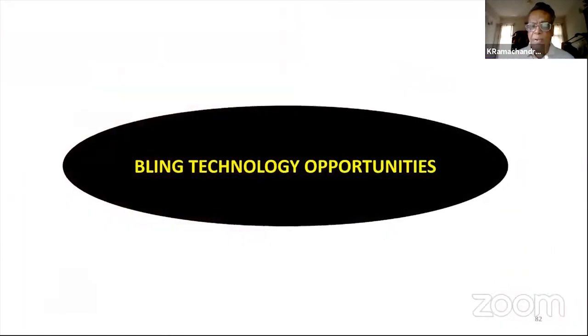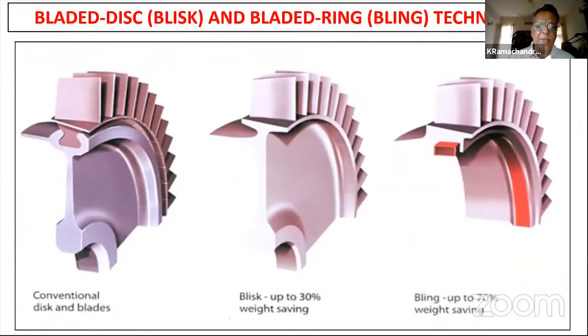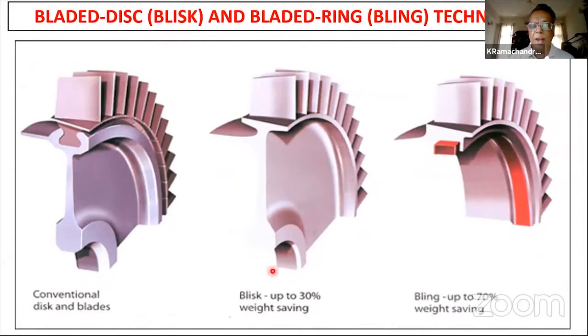I mentioned about bling. What is bling? If you look at the conventional design, independent blades and discs, which is going to be replaced by what I said as IBR, where the blades are integral with the rim, and the size, the shape of this becomes smaller, and you get at least 30% reduction in the weight of the part. But today we are going to talk about a bling, the bladed ring, where there is no web or hub like this. It's only one small ring of titanium for here like this, and the blades are in position. But it cannot do a very high speed performance. And therefore you strengthen that with the silicon carbide, any ceramic material, silicon carbide here, which is going to be fused. And this is the technology.